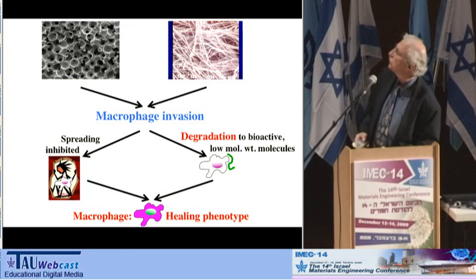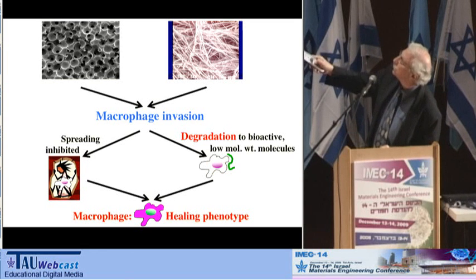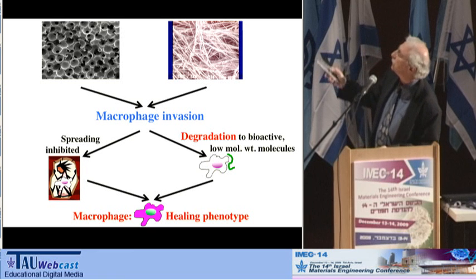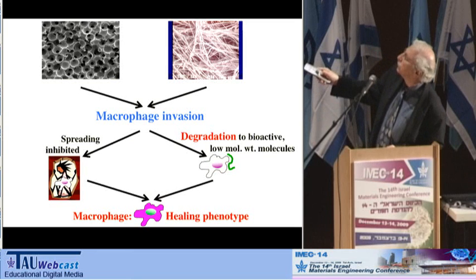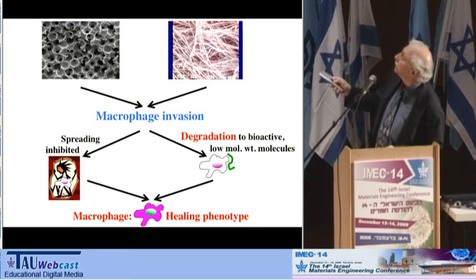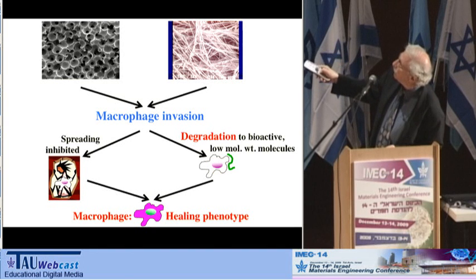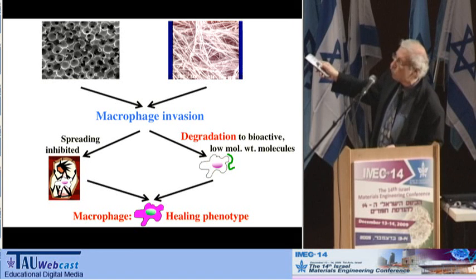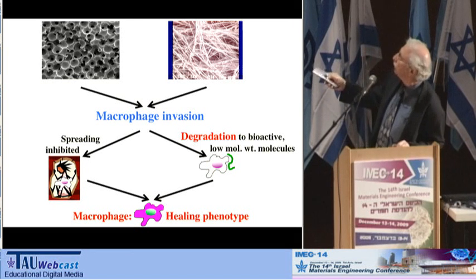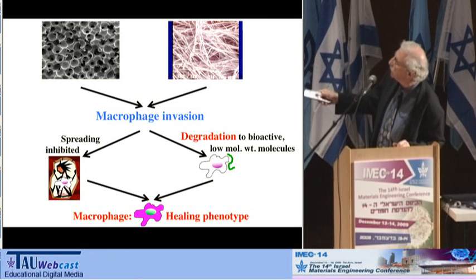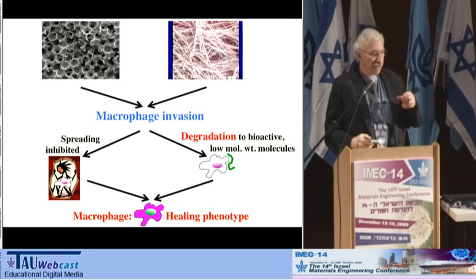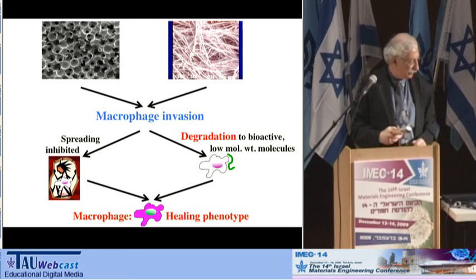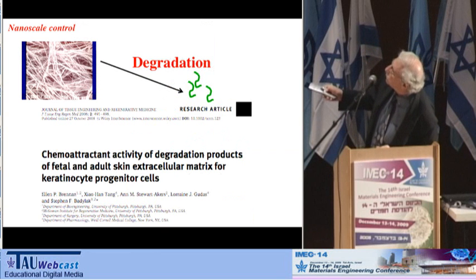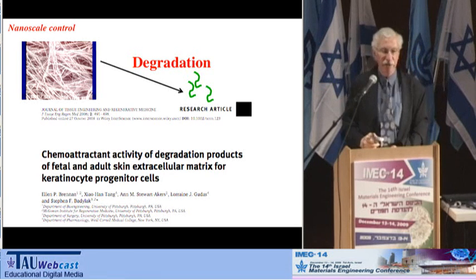Just to go back to Dr. Badylak's material, you'll notice the pore structure here looks nothing like our highly organized pore structure, but we believe it works by a completely different mechanism. Both materials are heavily invaded by macrophage cells, but in the case of Dr. Badylak's material, since this is biological, the macrophages degrade it to low molecular weight peptides, and we believe these peptides are recognized by the macrophage and lead to the healing. In our case, the macrophages are inhibited from spreading, and that drives the macrophage into this phenotype. So that's a hypothesis about what may be going on here. In fact, Dr. Badylak published a recent article showing the strong biological activity of the degradation products of this material.